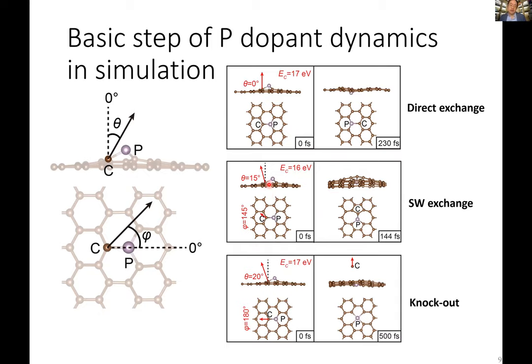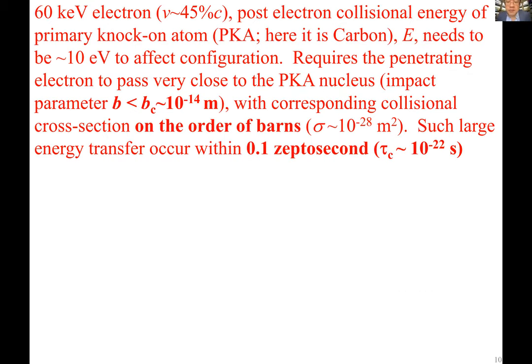And then there is also this scattering cross section where there is an angle theta and phi, where you can sample the direction of what we call the primary knock-on momentum. And depending on the angle, you can either have direct exchange, the 90 degree rotation, or knockout from the simulations. So here are some numbers. We say that this 60 keV electron, 45% of the speed of light, has to get within 10 to the minus 4 angstrom from the carbon nucleus to give it a 10 eV energy.